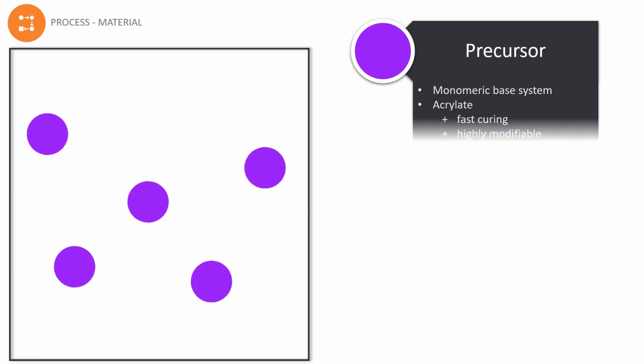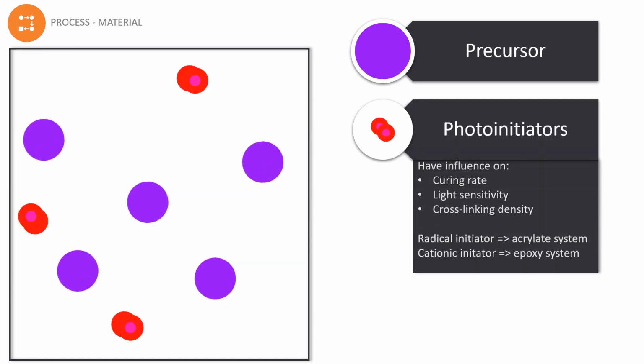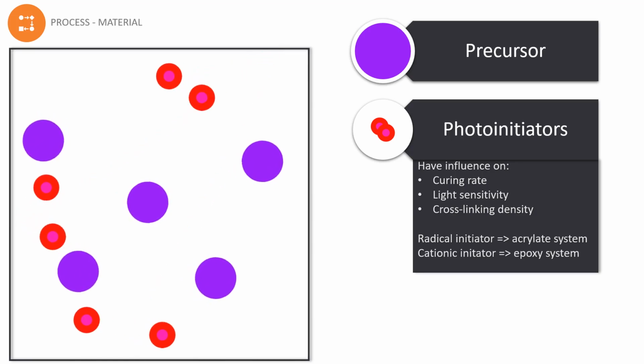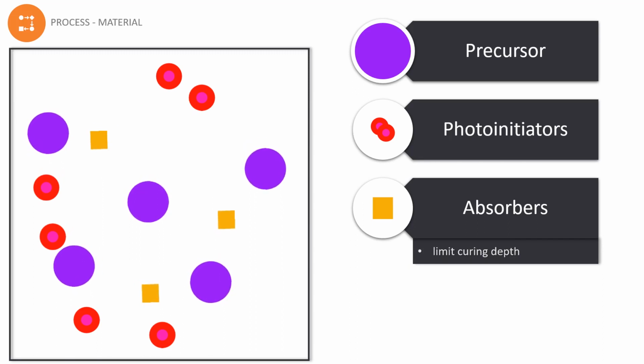The second ingredient are photoinitiators. They are of great importance because they determine the rate of the curing and also the light sensitivity of the resin. They are responsible for the cross-linking density and therefore affect the mechanical properties of the finished part. There are two types of photoinitiators, radical and cationic. The radical initiators are used in acrylate systems. They absorb incident radiation and lead to radical formation, which starts the cross-linking chain reaction. Cationic initiators are usually used in epoxy systems and form cations instead of radicals. The third ingredient are the absorbers. They limit the curing depth. This is especially important to enable complex geometries with undercuts and areas which should not be cured, and also to reduce aging effects by UV light. Most commonly, benzotriazole derivatives are used.